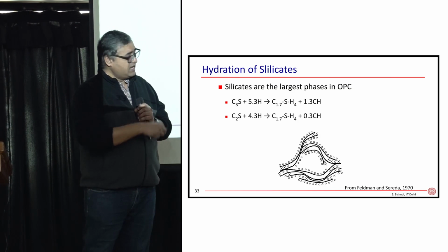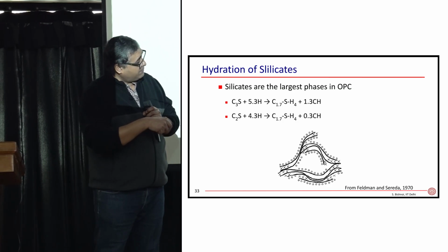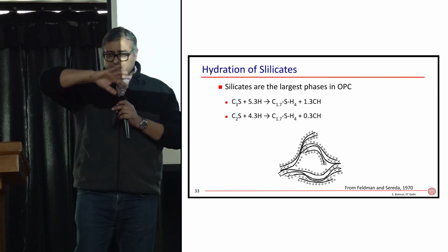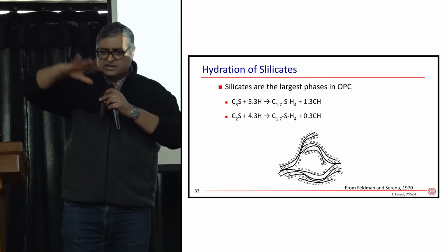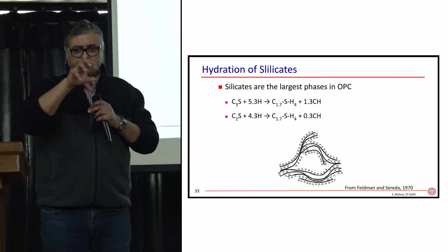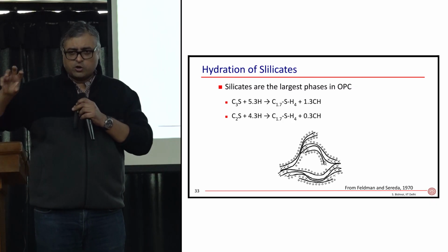Here, this is the interlayer water. And then there is water trapped between these. These sheets are just growing randomly, like foils at different places, and you've got empty voids where small pockets of water are trapped.